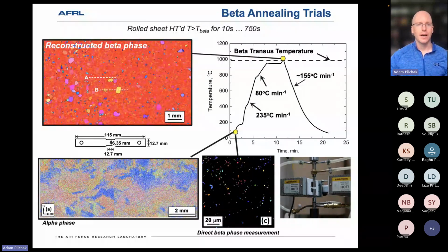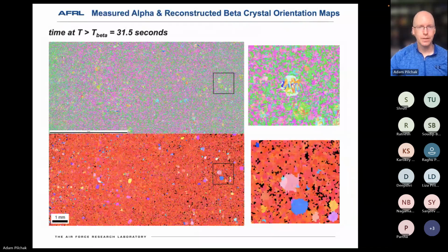beta phase texture. But what we saw at the shortest annealing times, and I'll show you in a moment that this persists over several minutes, we saw that all the beta phase orientations disappeared except for this cube-like texture. And there are some reasons for that we'll get into in a little bit.